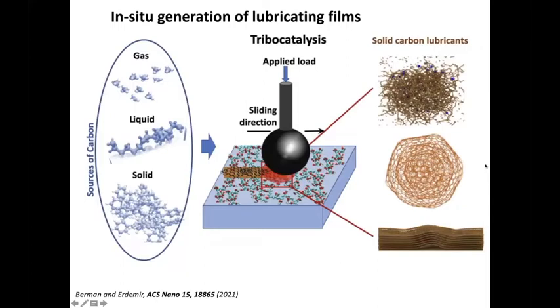At the same time, we're looking at this concept of the in situ generation of the lubricating film and how we can use gas, liquid, different solid sources of carbon, the same way as we observed for MoS2 plus diamond, when diamond played the role of the carbon source to reconstruct the more favorable solid carbon lubricant conditions. So how can we use this whole dry sliding system, when we have the stress and temperature assisting the materials reconstruction, to get this better tribological behavior, and to receive tribological systems that can give us carbon-based systems that can get us to the superlubricity state across these various conditions.